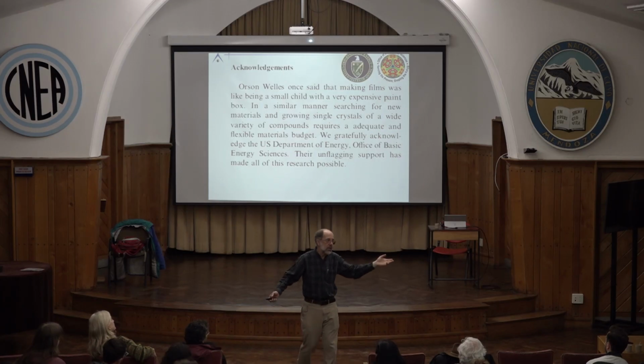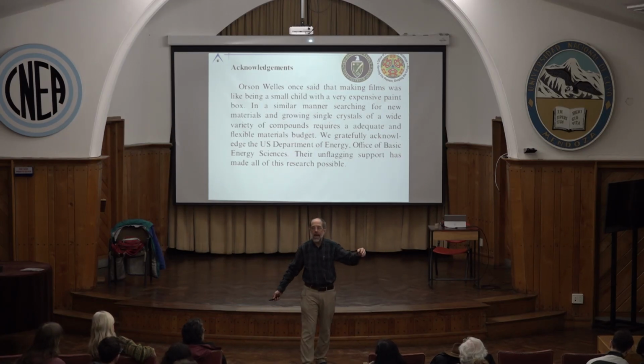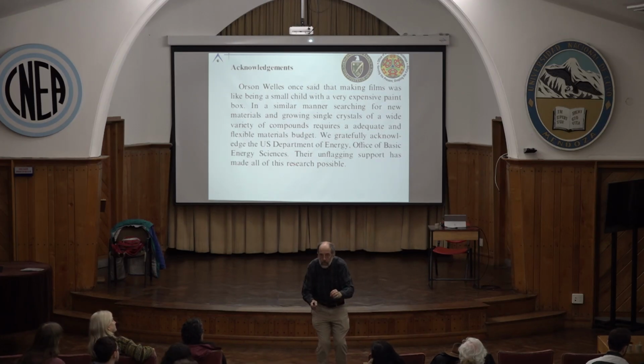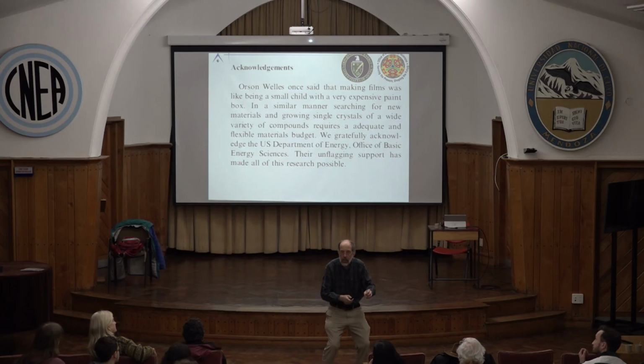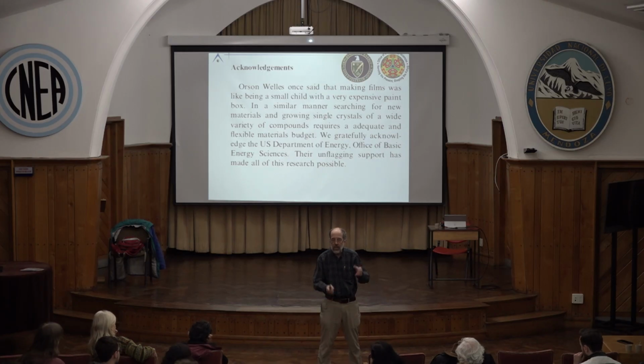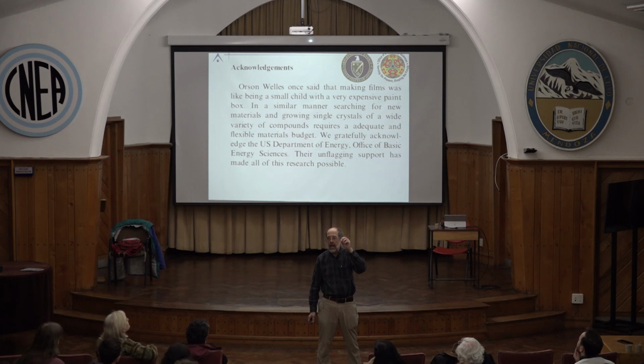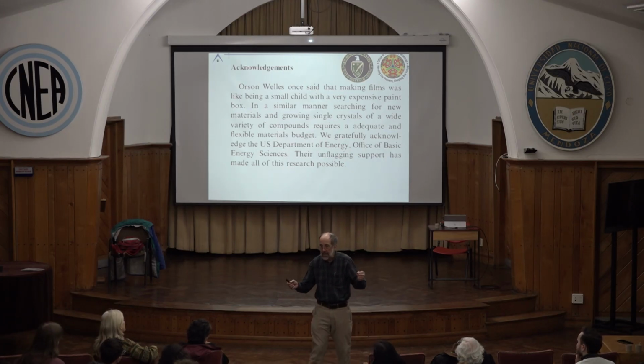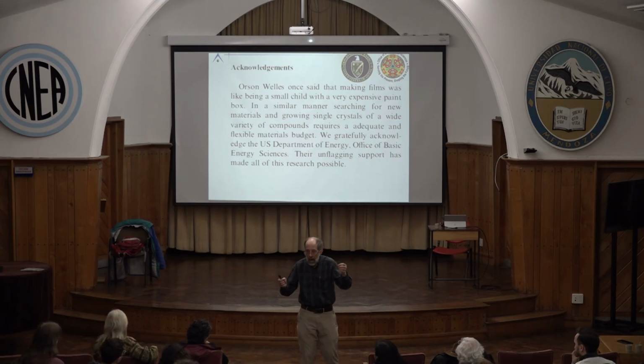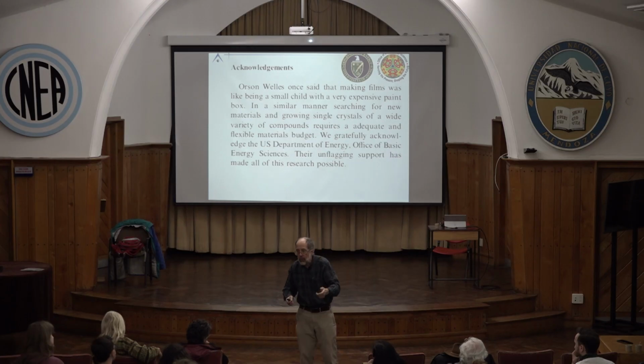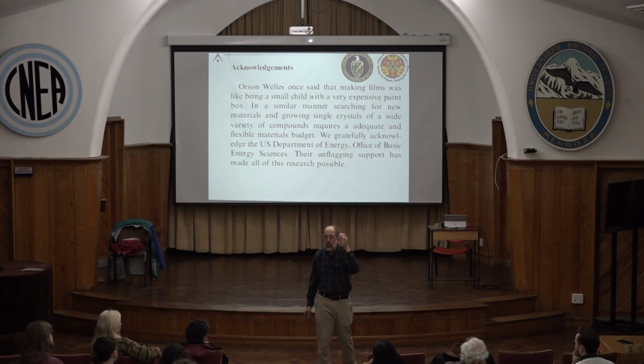I also work, and I haven't talked about this at all, we were looking for practical ferromagnets that aren't rare earth or use cheap rare earths. Okay? Cerium is a throwaway rare earth at this point. There's lots of cerium. If you can find a high Curie temperature TC ferromagnet with good anisotropy, and it's amazing, when you're looking for a ferromagnet and a superconductor, it's the same. You want a high TC, different Cs. You want anisotropy in pinning. You want pinning of vortices, you want pinning of magnetic domains. So we worked on that. We found a very interesting cerium cobalt with a little bit of magnesium and other stuff. That turned out to be applied.